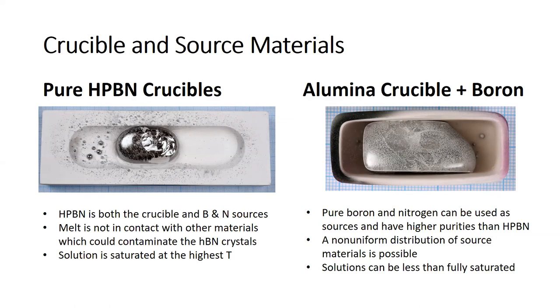We can also play with how we distribute the boron, and we can use that advantageously to grow larger crystals. And then we can also produce crystals from solutions that aren't fully saturated. So we can actually go above the saturation condition and then cool.